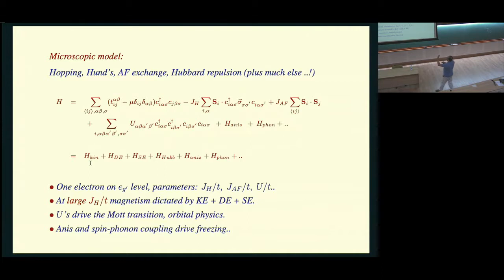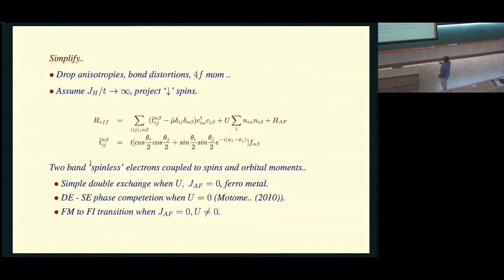Now, for the sake of convenience, I will push this Hund's coupling to a large value, so that I'm not worried about the electronic spin anymore. I'll look at the spin polarized case, like in the manganite problems. If you went through all of this, you'll end up with a model which has a simpler structure. It has to do with the orbital interaction between two electrons on the same site. The spins are parallel, so there is no up-up interaction anymore. So there is an orbital Hubbard model, a spin-dependent hopping between sites.